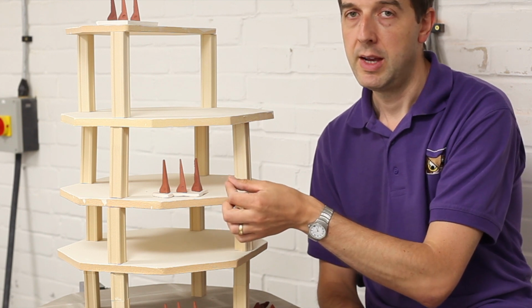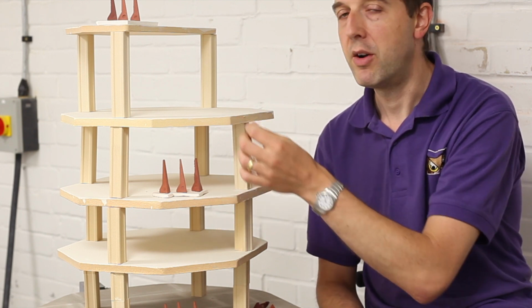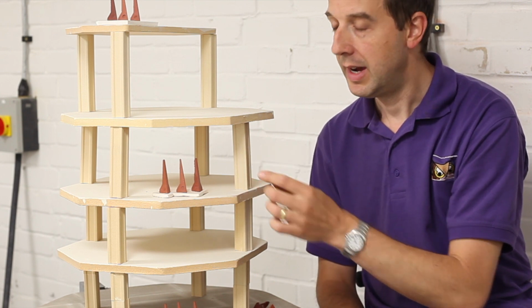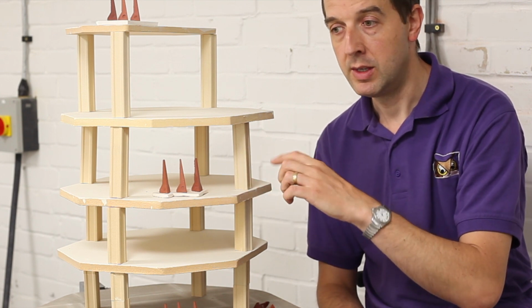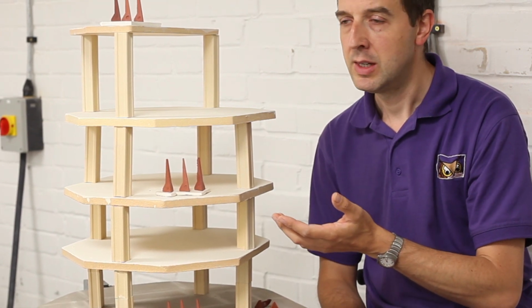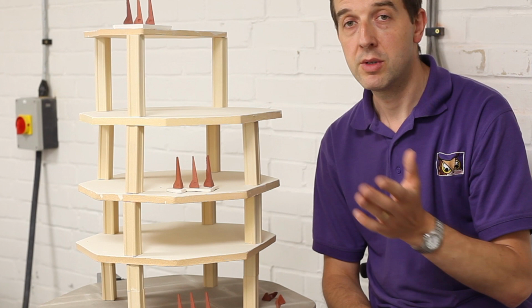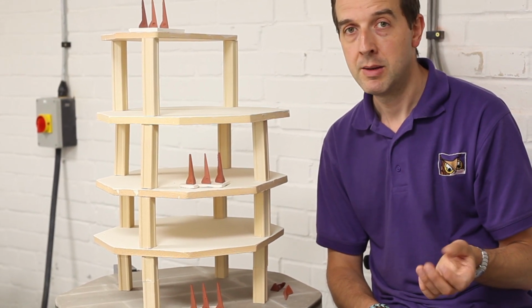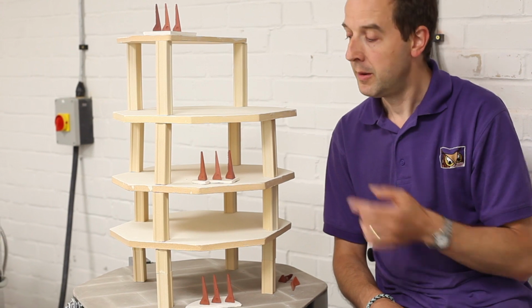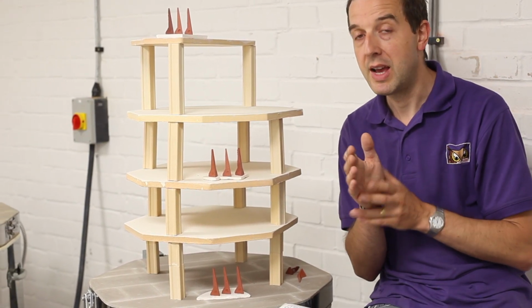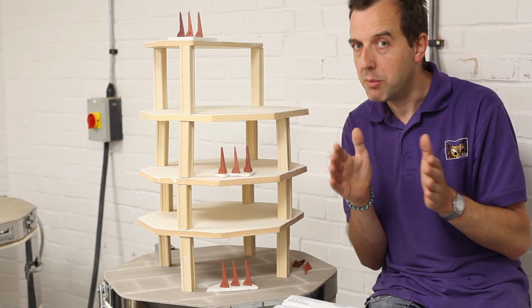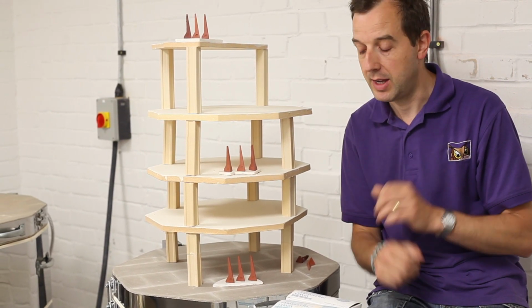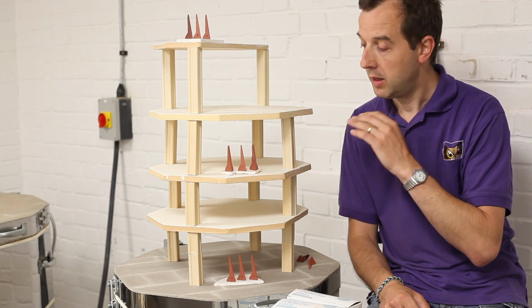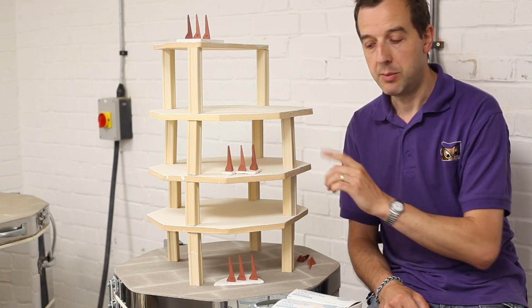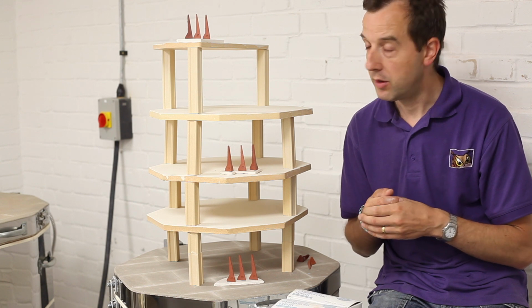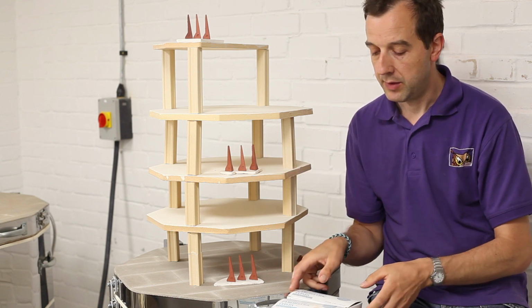a 06 for example, and in one area of the kiln it was firing a little bit cool and wasn't able to bend that cone, that's all very well, but it doesn't tell you exactly what temperature it got to. It tells you it hasn't got to a 06, but did you even get to a 07? If you put in 3 cones, you're able to carefully, accurately judge exactly how much heat work has been generated in that part of the kiln. So that's why 3 cones to test 1 temperature. So for this 06 firing we'll need 05, 06, 07.